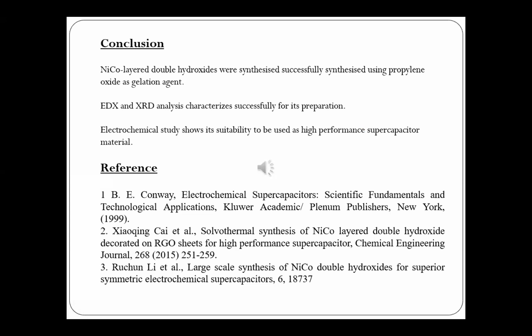In conclusion, this nickel cobalt double hydroxide was synthesized successfully using propylene oxide as a gelation agent. It was successfully characterized and its preparation confirmed. The electrochemical study shows its suitability to be used as a high performance supercapacitor material.